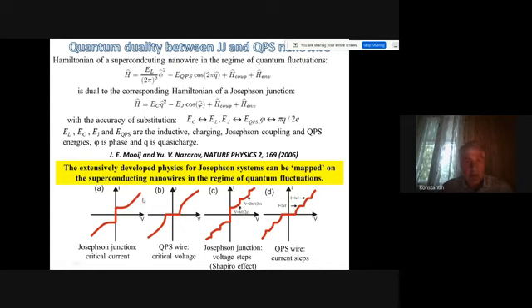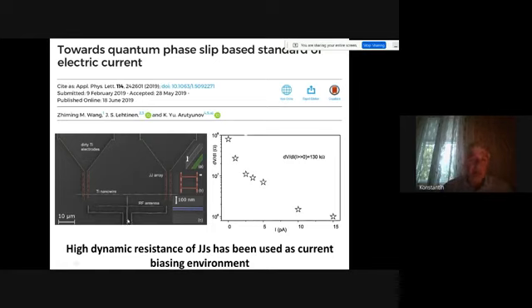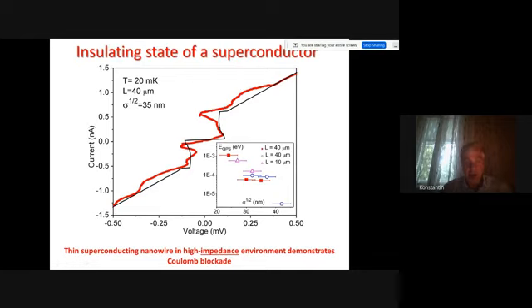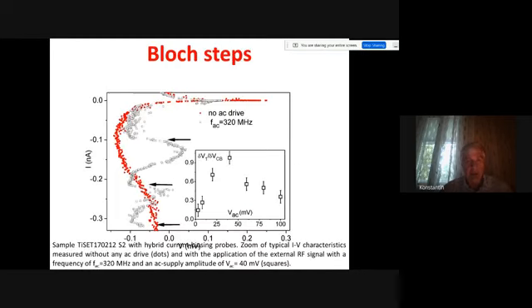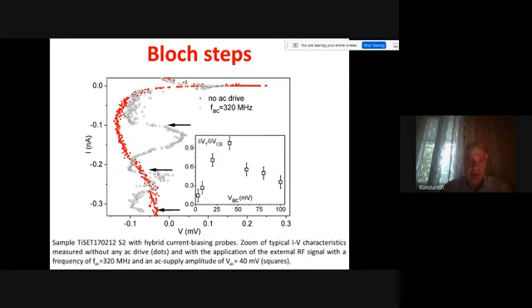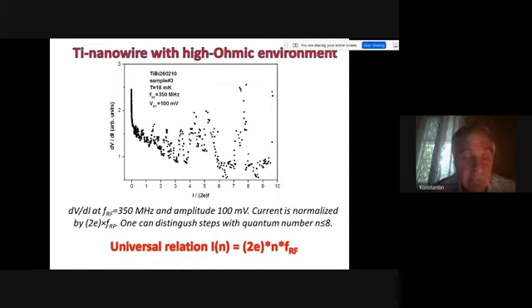In our dual system, we have a rotated IV characteristic which shows Coulomb blockade. If now we apply high-frequency radiation, following this duality, we should have quantized steps of the current, and this is now our objective. So again, we fabricated a sample, a very narrow titanium nanowire, to be sure that it is in the regime of quantum fluctuations, and it was surrounded by very high impedance arrays of Josephson junctions. The IV characteristic is shown here, without any external electromagnetic radiation. But when we apply radiation, some singularities happen at positions indicated by the arrows.